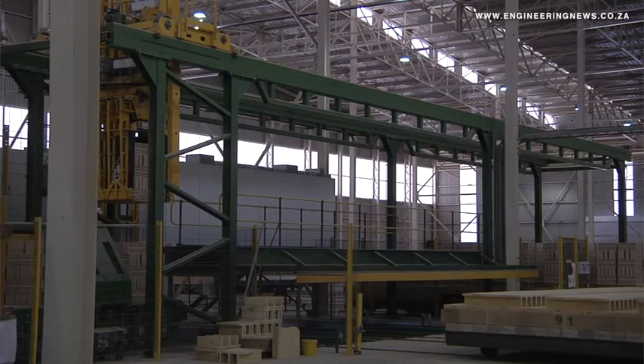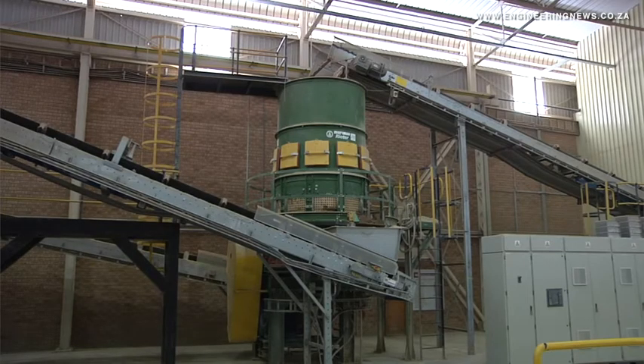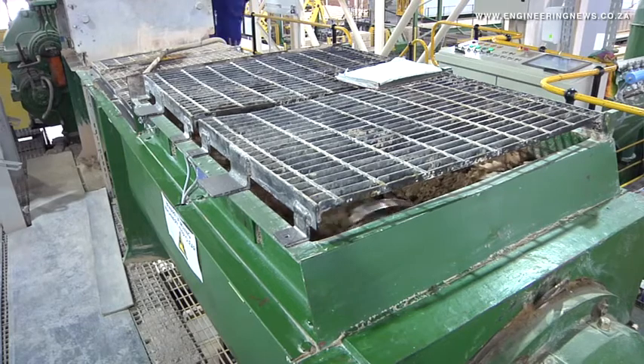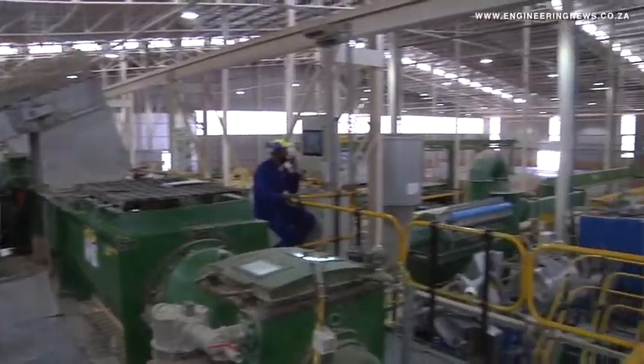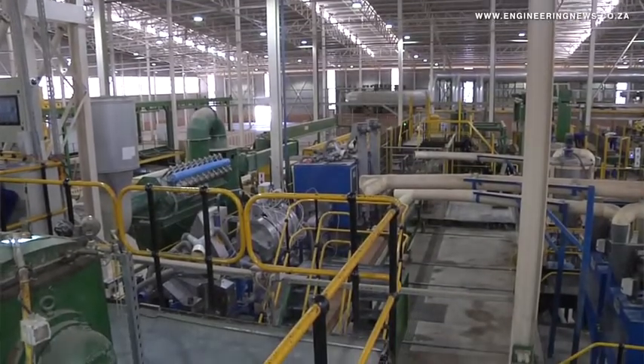The specifics really go around the water addition and the amperage on the extruder, which give us a stiff column and control of the stiffness of the column, so the bricks are consistent in size because of the water absorption and the uniformity of the column of the brick. We also have automatic handling so the product is not touched by human hands, and every brick is packed exactly the same way, over and over again.